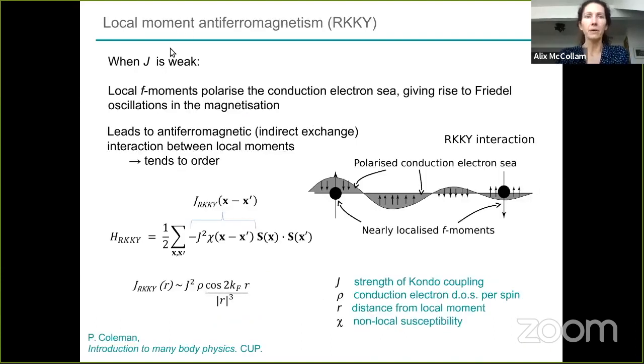Okay, when we have a weak coupling, so we're not in the limit where we have a strong Kondo effect and the f-electrons are actually hybridized into the conduction band, you still get an interaction of the conduction and the f-electrons, and you get a polarization of the conduction electron C. If this is a nearly localized moment, you get a disturbance or an exponential decrease in the electron density here, and then this continues as a Friedel oscillation, or a kind of sinusoidal oscillation, as you go further away from the original disturbance or the original localization. So this polarization of the conduction electron C is the well-known RKKY interaction.